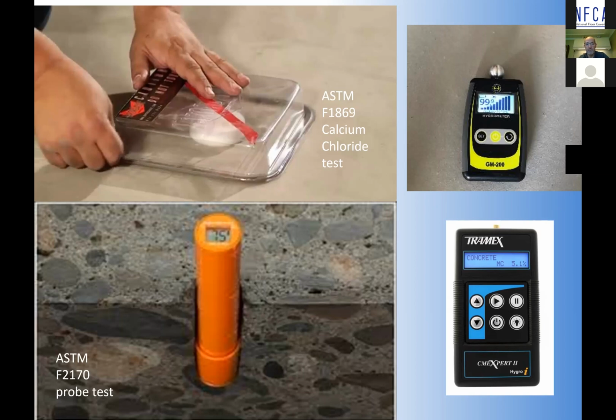So you can still do a probe test, but also understand that if you've got a radiant heated gypsum pour, you've got to be extremely careful that you don't hit a hydronic line, or if it happens to have electric heat, you've got to be careful you don't puncture it. So that's where the calcium chloride topical test could work better in those applications. And there are also surface meters, although they are not an industry standard, they're still very applicable for some quick non-destructive testing to get an idea of where your moisture levels are. So even though it's a gypsum product and it's thinner, you still have to go through the process of doing moisture tests.